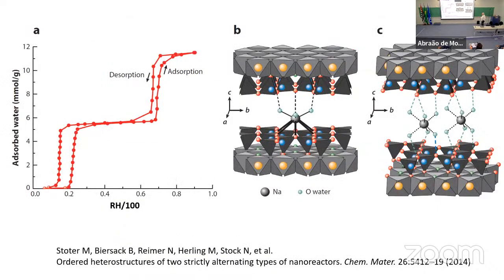One interesting thing is, what do we mean exactly by one and two layers of water in the interlayer space? The water goes in there because water is a dipole, and it is attracted to the cations sitting in there. And the water coordinates itself with the cations. In the one water layer situation, it's like this, a coordination number of 3 typically for this clay. And for the two water layer situation, which is here, a coordination number of 6 typically. These round things here are water molecules.